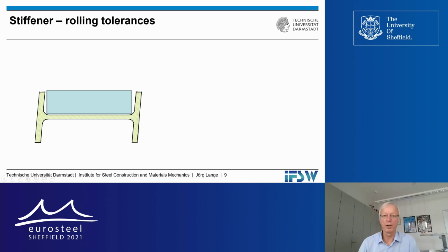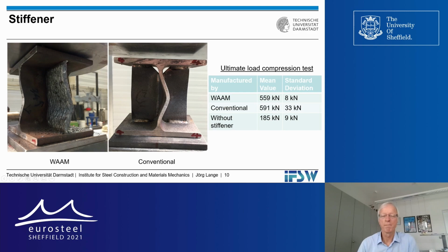This can be avoided if we use 3D printing. Here you see a stiffener on the left-hand side that was printed into a hot rolled beam, and on the right-hand side you see traditionally manufactured stiffeners. And we took the normal conventionally manufactured stiffeners and tested them, which gave an ultimate load, in this case, of 591 with a standard deviation of 33 kilonewtons.